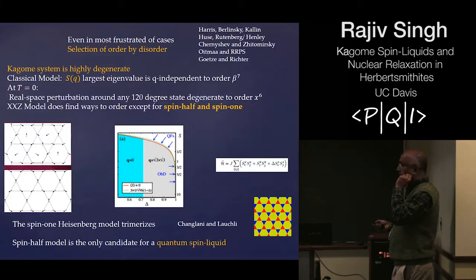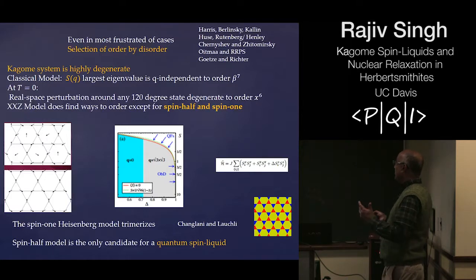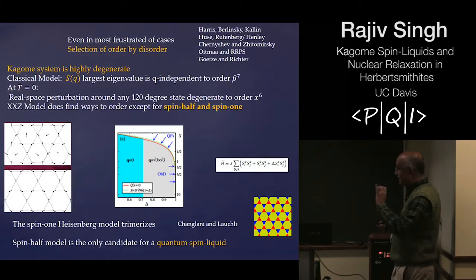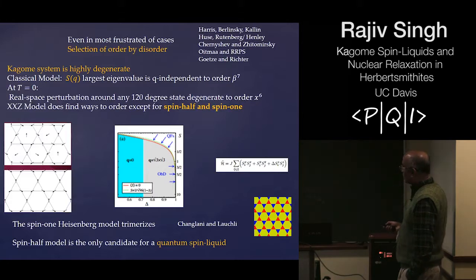So structure factor is a 3 by 3 matrix really for every Q value. And what one finds is that the largest eigenvalue is independent of Q up to some order, but then at some higher order selection happens and spins begin to prefer to order in a particular way. And the same thing happens actually if you study the system at 0 temperature basically. So you can show that if you start with any 120-degree ordered configuration and carry out either nonlinear spin wave theory or real space perturbation theory, it remains degenerate up to some high order, but then an order begins to get selected. But then if quantum fluctuation become too large, then they end up destroying this kind of order.